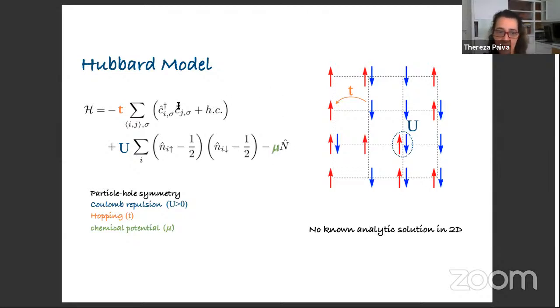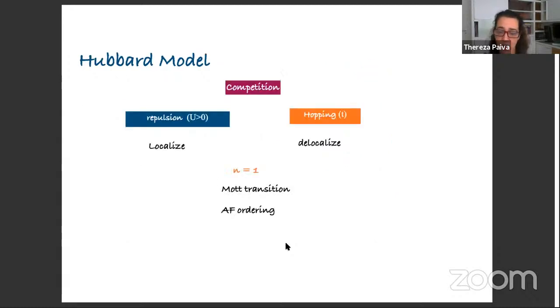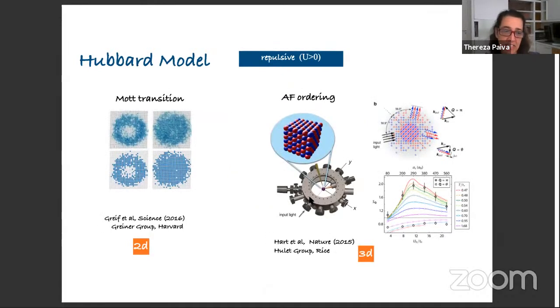And although it's a simple form, there is no known analytical solution for this model in 2D. And yet a lot is known. This model was proposed in the early 60s to study ferromagnetism in materials. But the basic thing is we have a competition between the repulsion term and the hopping term. And this tends to localize electrons or fermions in the lattice. And at half filling, we do have a Mott transition and antiferromagnetism. And this has been seen in optical lattices. The first time the Mott transition was seen was back in 2008.